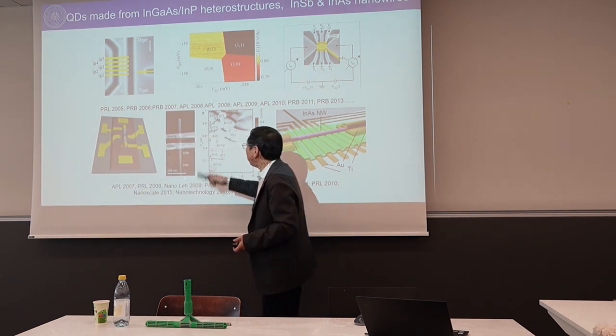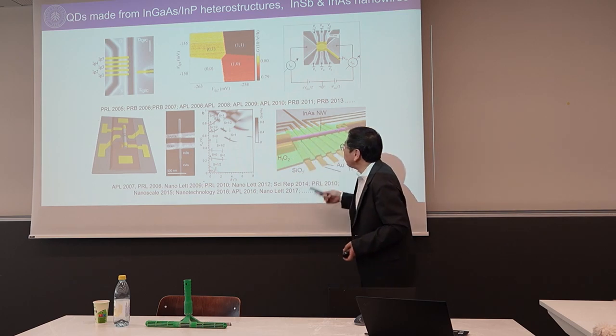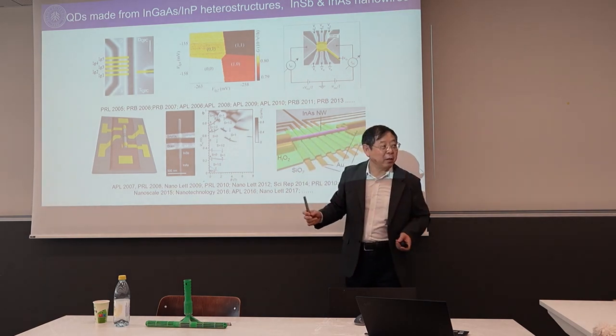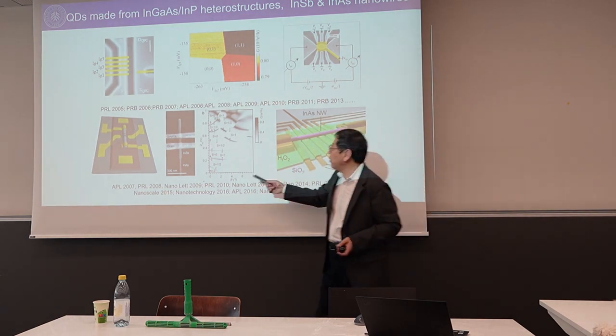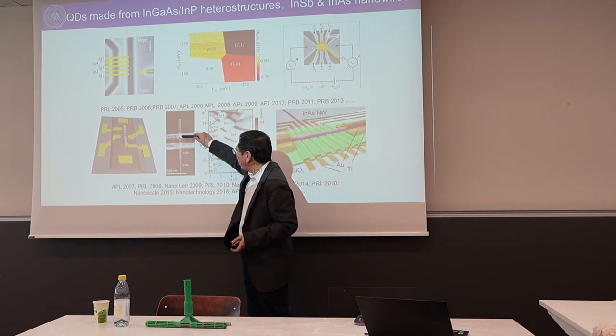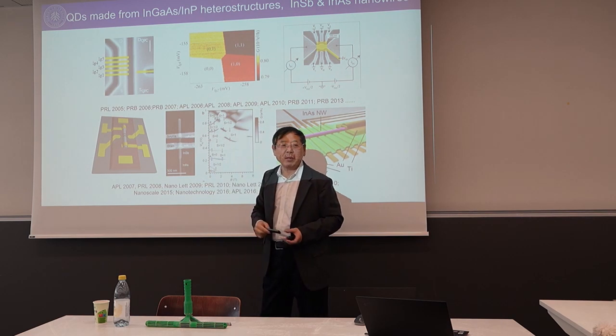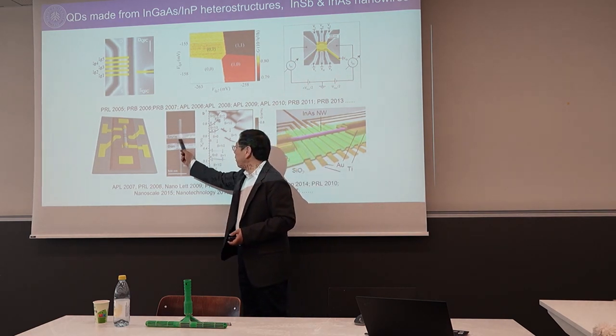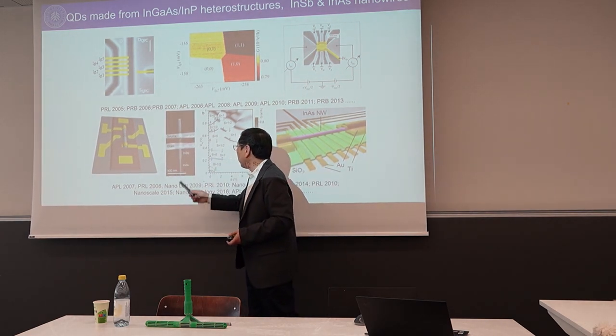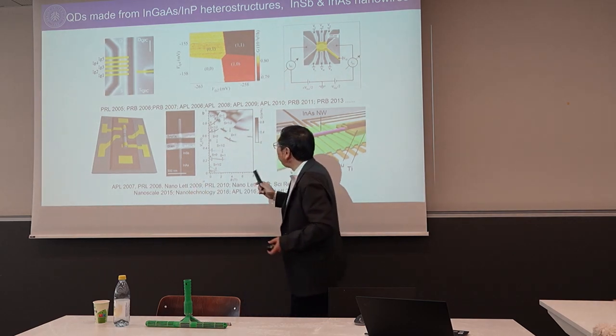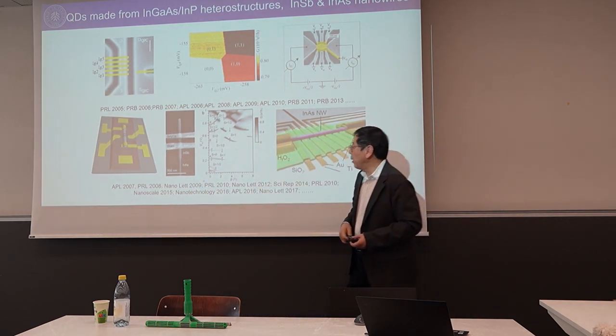So that is also something we work on. This work basically uses very good materials, indium antimonide nanowires. We can build a quantum dot with two sources. This is indium antimonide, very beautiful indium antimonide nanowires. So we can build one quantum dot here. Then we have a back gate, and then we can really map out states and also spins.